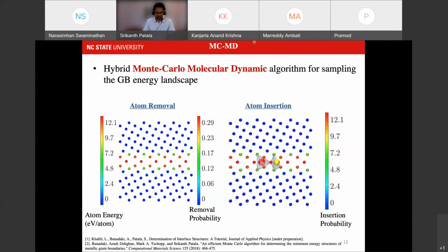But if you have, let's say, an alloy system, definitely, again, I think this goes back to one of the questions on ceramics too. Depending upon how spread out the variation in the composition might be, one might have to go to a larger system. But generally speaking, especially my interest in some of the more interesting topics here, which have to do with nanocrystalline alloy systems, segregation tends to be very focused or limited to the grain boundary, or maybe a few widths of the grain boundary. So we can get away with it.